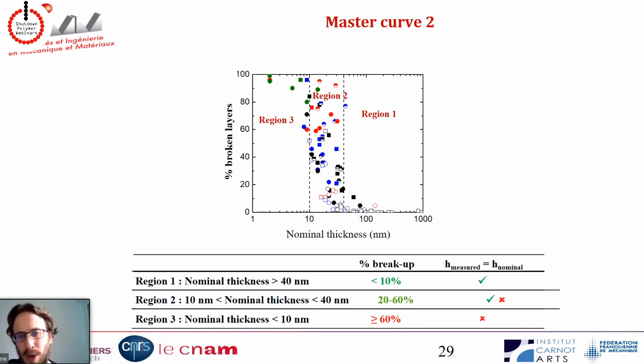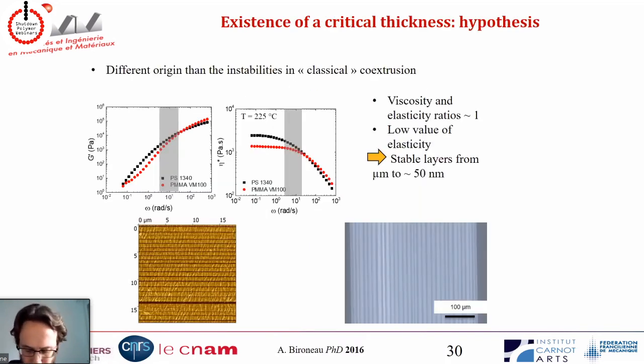So what it tends to say is that there is some kind of physical reason, independent of processing parameters, that explains why below 10 nanometers, everything is broken. The first reason you can think of is, okay, it's probably a viscoelastic problem. I talked to you about that before. In coextrusion at the micron scale, viscoelastic problems can create some breaking of layers.